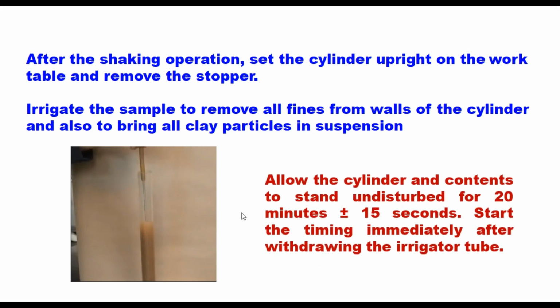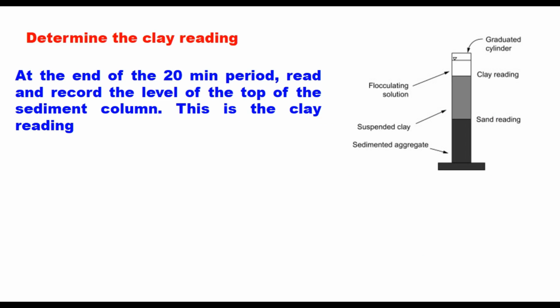Allow the cylinder and contents to stand undisturbed for 20 minutes plus minus 15 seconds, and this time should be started immediately after withdrawing the irrigator tube. Now determine the clay reading. This will be the position of three materials here. The bottom part will be sand or sedimented aggregate. The middle part will be suspended clay, and the upper part will be flocculation solution or working solution.